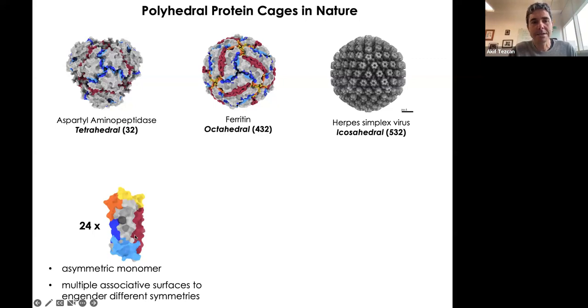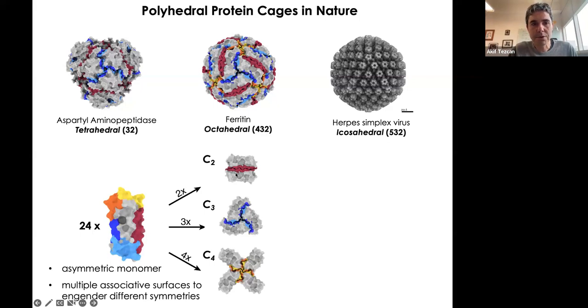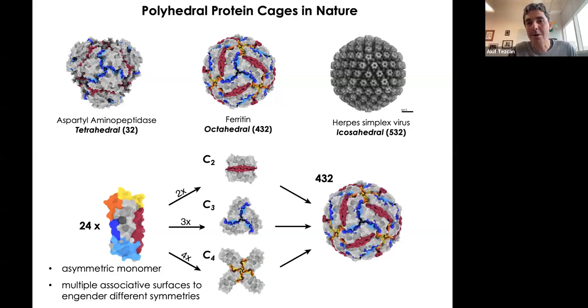And each monomer has to have a surface patch that forms its C2 symmetry. It has to have 2 patches, shown in blue here, to form a C3 symmetry. It has to have 2 other patches to form C4 symmetry that, like puzzle pieces, all come together to form this 432 symmetric octahedral unit with a hollow interior. So the problem is, how do we take an asymmetric monomer and design multiple associative surfaces at the same time so that it assembles into the architecture that we want?